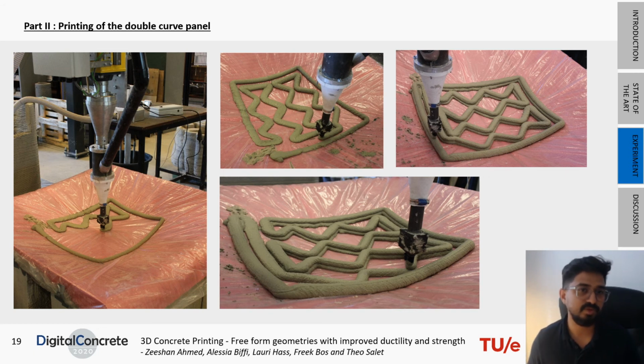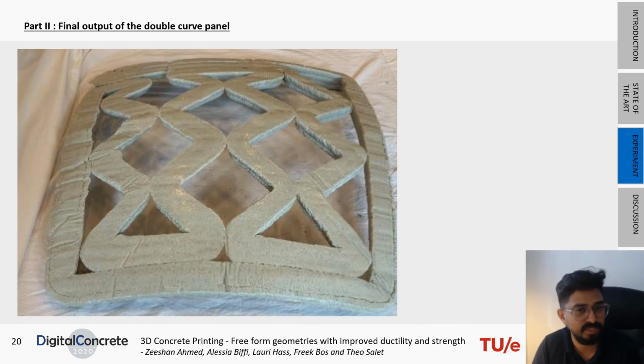During the printing process, as you can see from this figure, some of the points of the woven pattern were not attached clearly, which was corrected by increasing the overlap between the printed filaments, and secondly by adjusting the extrusion rate. Finally, you can see the printed panels which were developed during this project.